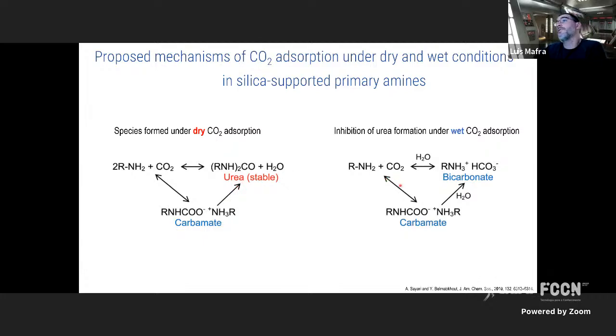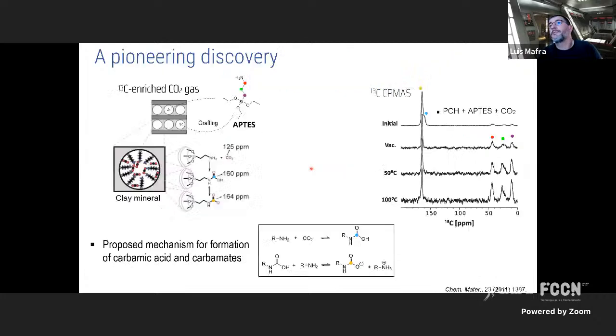At the right side, you have a different path. Here you need only 1 mole of amine per 1 mole of CO2, and you form carbamate, and then with water, you can form bicarbonate molecules. Okay, so the stoichiometry is basically different. The other path doubles the stoichiometry, meaning that you have a lower CO2 capacity. It's very important to understand these paths, because one-to-one stoichiometry will increase the concentration of amines inside the pores, and this is very desirable, of course.